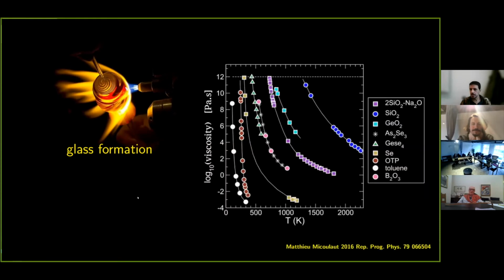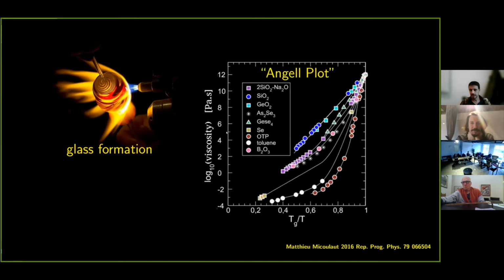So what are the big problems in glass formation? If you look at the viscosity, this on the y-axis, these are experimental data of the viscosity versus temperature for various types of liquids. What you see is that the viscosity grows by several orders of magnitude upon reducing the temperature. The way that the viscosity of these materials changes differs between different materials. The generic way of representing these data is plotting them against the inverse of the temperature, where the characteristic scale is the glass transition temperature, which is just an arbitrary scale that is set by requiring that the viscosity at the glass transition temperature is 10 to the 12 Pascal second.